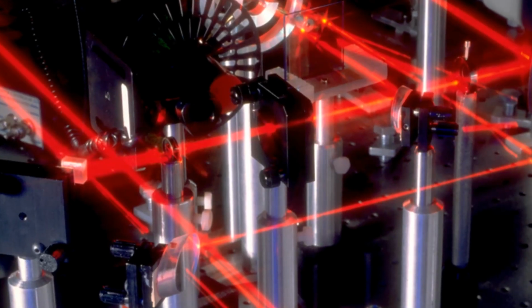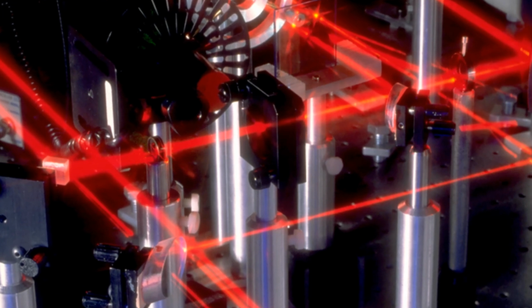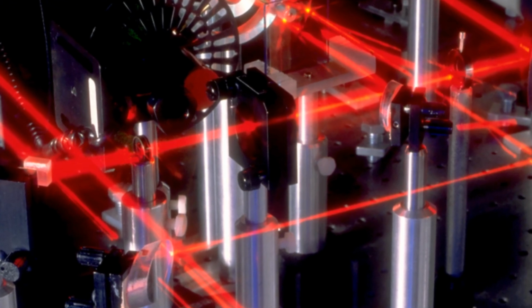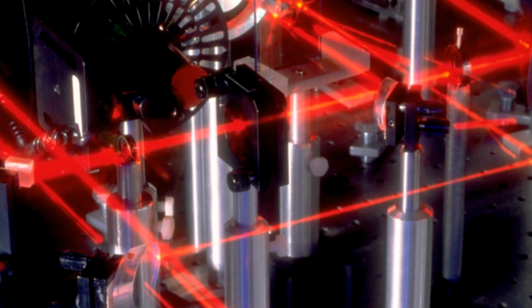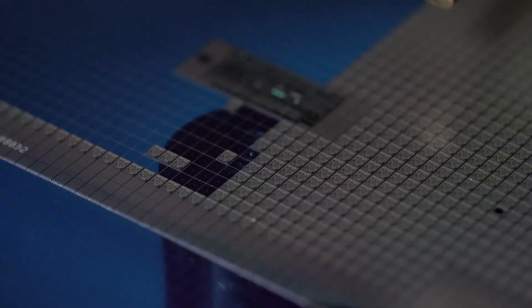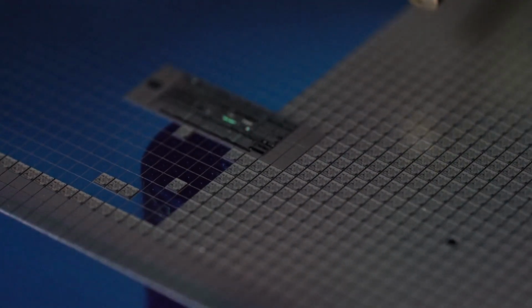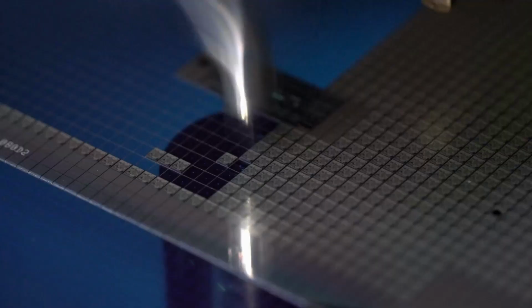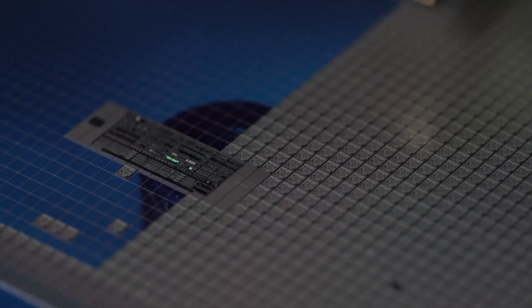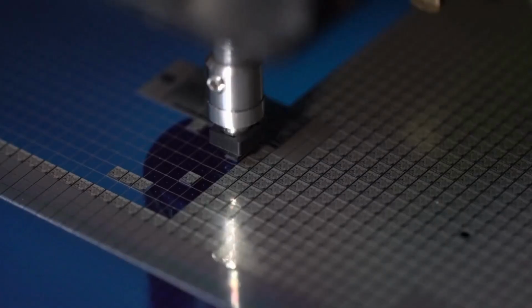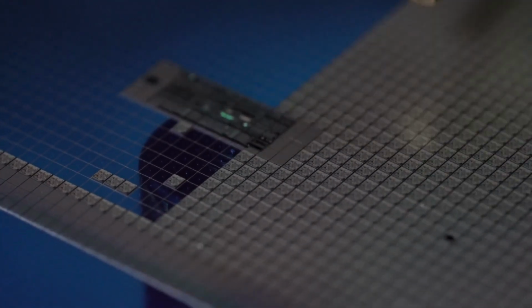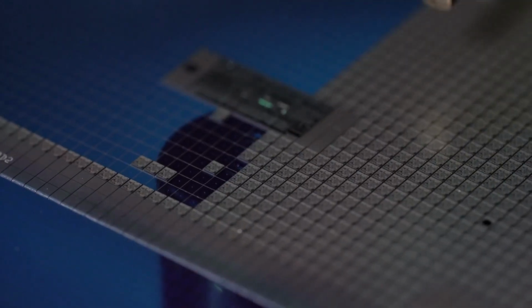The solution to the thermal problem at the cell has existed for over 30 years. It was not developed for solar. It was developed for lasers. A high-power laser diode has the same problem as a concentrator solar cell. A small semiconductor die, generating intense heat, bonded to a heat spreader with almost no margin for temperature rise. If the die gets too hot, the laser fails. The same physics, the same geometry, a different industry.